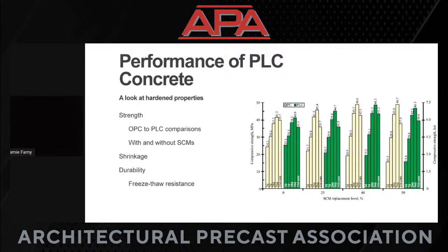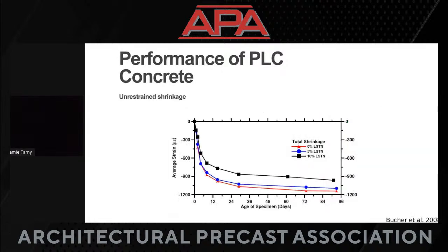Now, I focused on shrinkage and durability. I want to talk about those a little, especially the freeze-thaw resistance aspect of PLC mixes. But for shrinkage in particular, I think, precast, you make your materials and then you send them out to the job to be erected on site. So we've got a comparison of our total shrinkage of, in the red, a 0% limestone to a 5% in blue and a 10% limestone in black. And this is showing the average strain, right? So the larger the strain, the greater the shrinkage.